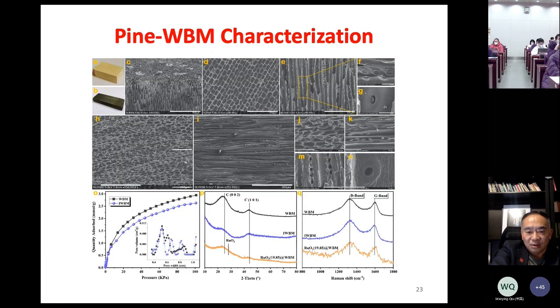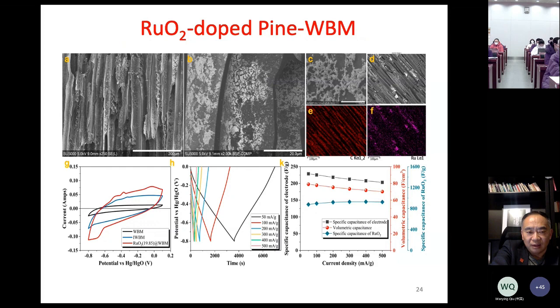I will not show the details here, but we applied BET analysis, XRD, and Raman to study structures. What you can see here is pine wood biochar; the top one is untreated and the bottom one is compressed. We also doped the biochar with active materials like ruthenium oxide to increase the energy density as well. Here are some results showing the film structures of those doped biochar, and the distribution of ruthenium.